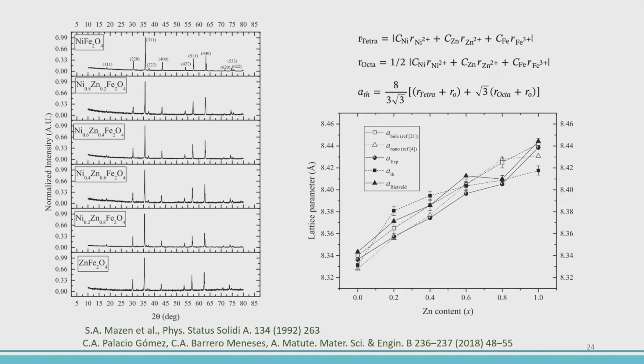So if we know this, of course we can determine this by using just, but we have here 3 variables and just one equation. Yes, 3 unknowns and just one equation. So it is difficult. We have to combine with different methods. But this is a method that can confirm that our guess about this cationic distribution is determined.